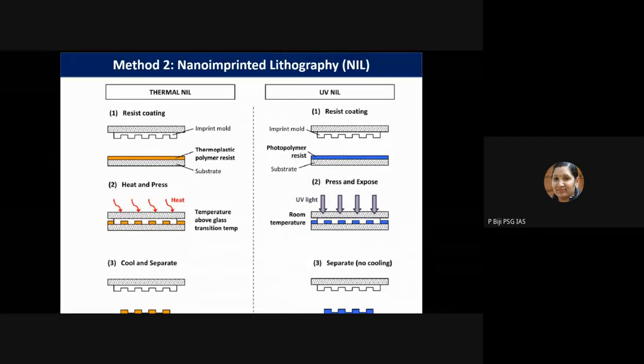So in the case of UV NIL, after the resist coating, you expose this film to UV light for curing. So you don't require any further cooling into that. But in our case, we have used thermal NIL.